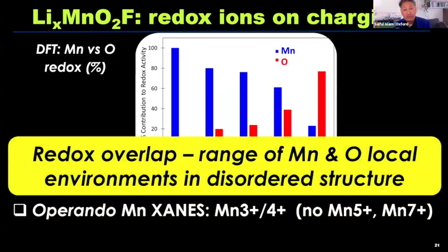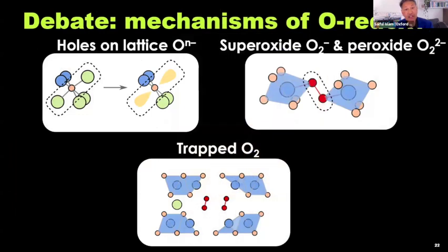So let me summarize. The redox overlap here is there's a range of manganese and oxygen local environments in this disordered structure. And that's why there's some redox overlap between manganese and oxygen. So the next question is, what is the oxygen redox species? And there's a lot of debate about this. Is it localized holes on oxygen, for example, O-, shown on the top left? Is it dimerization of oxygen to form superoxide or peroxide species? Or is it full dimerization to form molecular O2 trapped in the material? All three have been proposed, and there's evidence for all three.